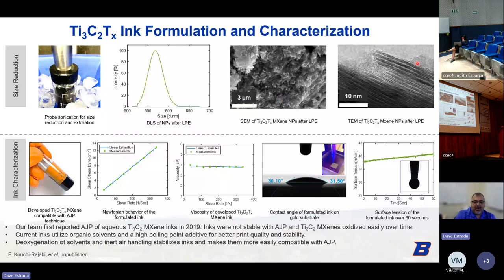We're using, right now, a mix of ethanol and ethylene glycol. That gives us a nice Newtonian behavior for the ink, low centipoise for the ultrasonic atomizer. Then we looked at contact angle to understand wettability on our printed gold films, and also just looked at the surface tension to make sure we're in that jettable window.